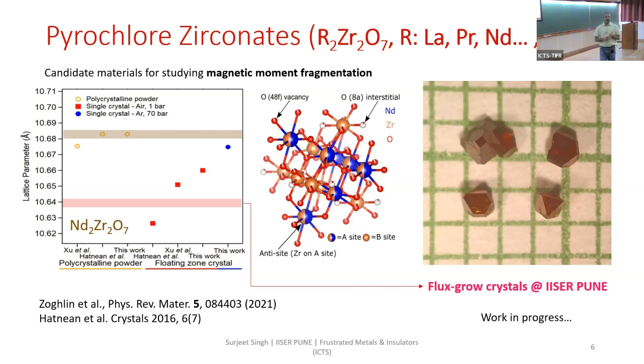B, they undergo an order-disorder phase transition at high temperatures. So when you crystallize them, they crystallize in a defect fluorite structure, and only when you cool them further down, they transform into the pyrochlore structure. And there's a subtle difference between the defect fluorite and pyrochlore structure, which is very important actually, because in these